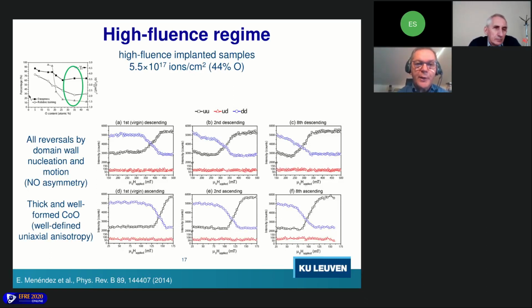And the reason for that is that in the high fluence regime, you really are creating a very thick and well-formed cobalt oxide, which is stoichiometrically correct, which has a well-defined and very, very strong uniaxial magnetic anisotropy. And this is a regime that you cannot reach by simple oxidation of a magnetic layer. So here I would say that the process of ion implantation creates a modification of the magnetic properties in a way that you cannot reach by natural oxidation.